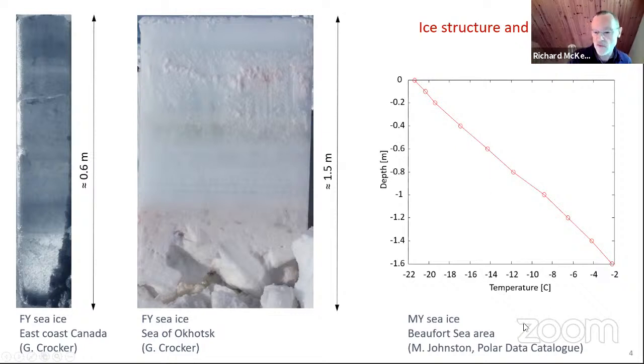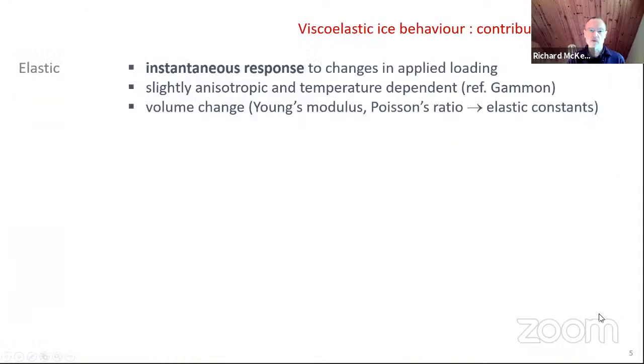I've shown here on the right a temperature profile that Michelle Johnson took from some Sachs Harbor experiments. You can see that it starts at the water temperature of -2 at the bottom surface, and the profile is approximately linear through the depth.